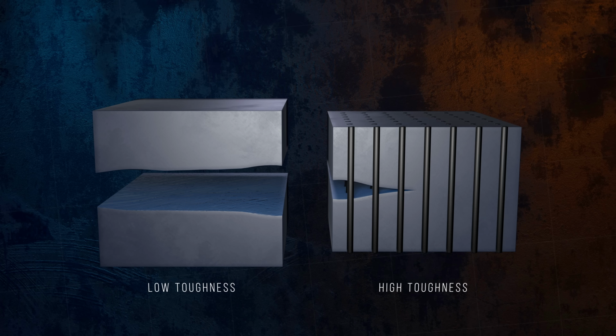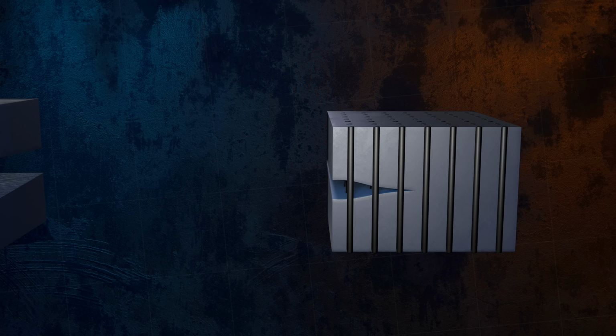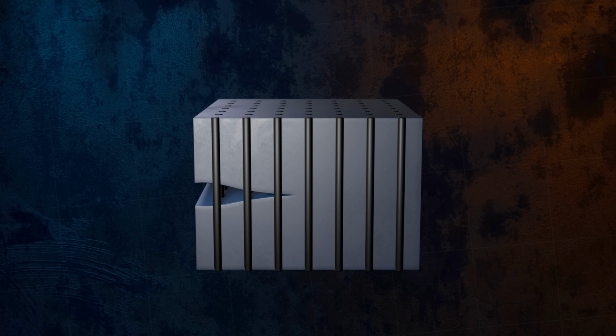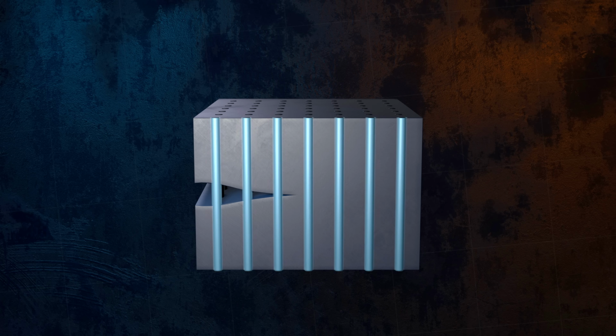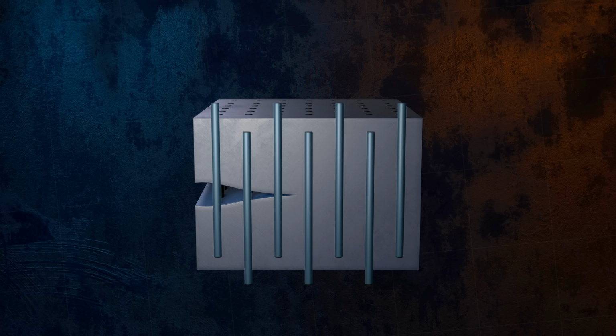Unlike polymer matrix composites, where the aim is to have a strong bond between the matrix and fibers, so that loads can be transferred between the two, in ceramic matrix composites, the fibers are coated to allow them to slide somewhat within the matrix, so that cracks in the matrix don't overstress the fibers. The resulting composite is extremely resistant to temperature without being too brittle.